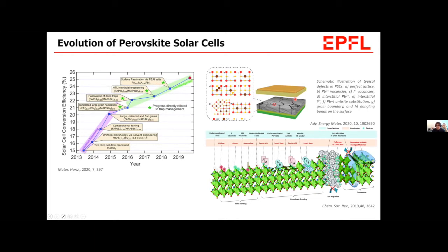There are different types of traps, for example vacancy or interstitial defects, substitutional defects, grain boundaries and dangling bonds, etc. Among these trap sites, grain boundaries and dangling bonds can act as deep level traps that should be minimized. So people have attempted various ways to reduce the density of defects by so-called trap passivation or defect passivation using Lewis acids or Lewis bases, or by introducing wide band gap materials, etc.